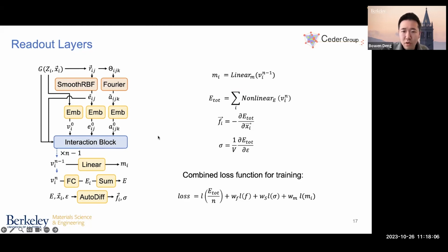After all of these interaction blocks, we predict the properties of the crystal structures by these readout layers. First of all, we use a linear layer to map the features on the atoms to the corresponding magnetic moments of the atom. In such a way, we apply these charge constraints to the atom embeddings to force them to have the information of their atomic charge. Second, we predict the total energy of the system using a non-linear mapping of the atom embeddings and the summation over them. The forces and the stresses can be calculated through auto differentiation of the total energy with respect to the atom coordinates and the cell. To train this giant neural network, we use a combined loss function that contains terms from the energy, the force, the stress, and the magmoms.